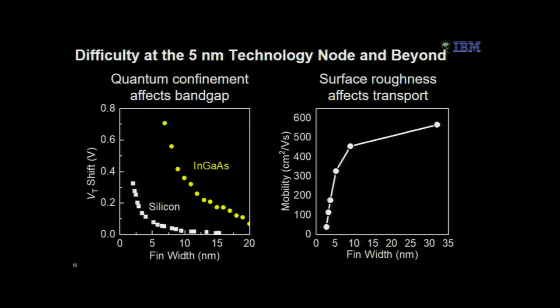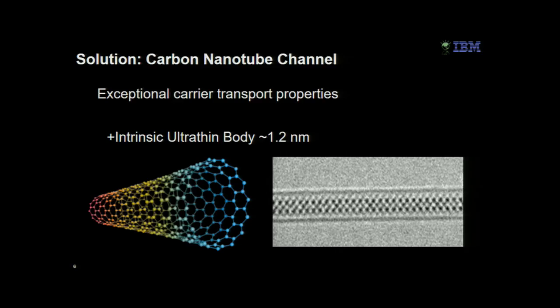Another problem is transport. The reduction of the silicon film thickness sharply reduces the carrier mobility due to enhanced surface roughness scattering. And the best material to solve this problem is, again, carbon nanotubes. They have not only exceptional electrical properties as what we just described, but also this atomically smooth intrinsic ultra-thin body of only 1.2 nanometer. And such an ultra-thin body could offer excellent electrostatics even for extremely scaled transistors, as what we